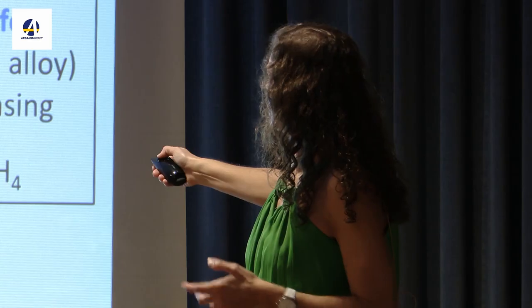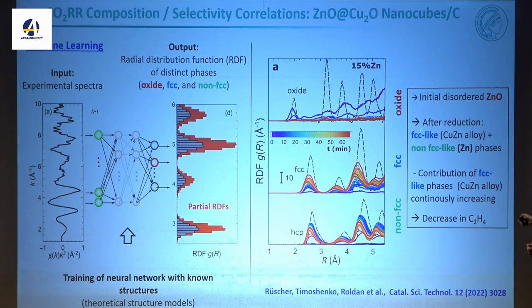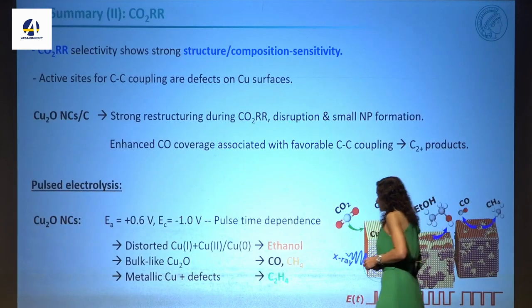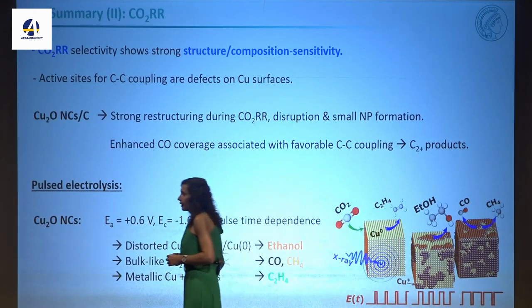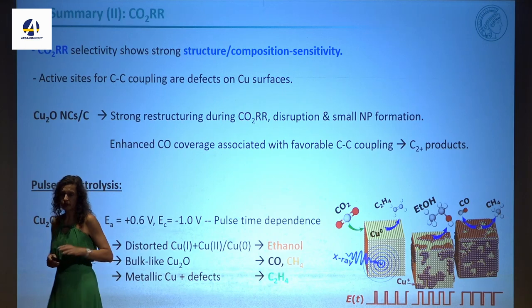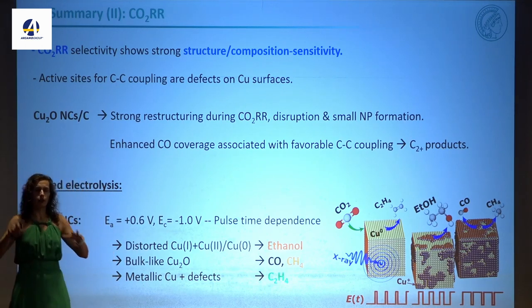So you can see that initially you have this disordered zinc oxide. After reduction, you make this copper zinc alloy that is FCC-like, and you also see non-FCC phases, zinc. But this here, the formation of this, is responsible for our deactivation. So to wrap this up, I hope that I could show you that these catalysts are restructuring, they are changing